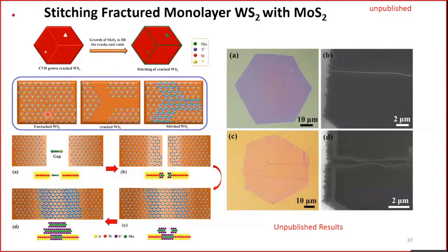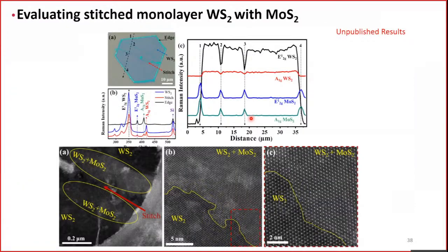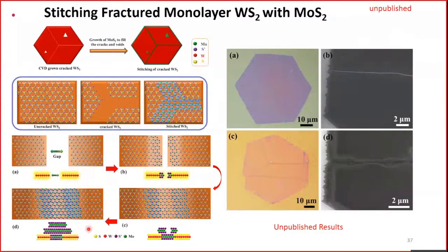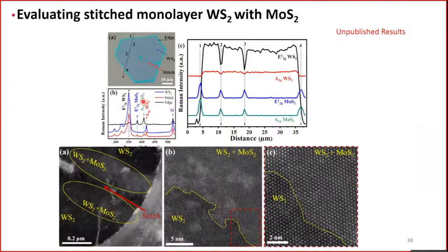The other aspect is, in some cases, we can also use fractured 2D material and again do atomic stitching. If, for example, there is already a fracture and WS2 is broken, then we do a regrowth. Wherever the crack is present, there the MoS2 essentially grows and stitches these broken bonds of WS2. Again, we have characterized very carefully and also looked at it in the aberration corrected microscope. We have found some interesting results with this kind of atomic stitching, both optical enhancement and also the contact potential goes up.